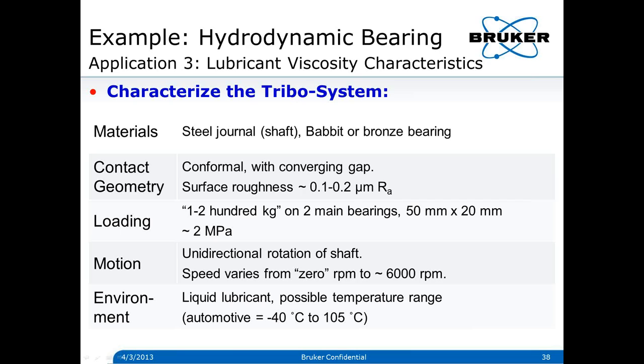Loading on a main crankshaft is roughly 1 to 200 kilograms on two main bearings about 50 mm in diameter and 20 mm wide — about 2 megapascals contact stress calculated as load divided by area. Motion is unidirectional rotation of the shaft, varying from zero to roughly 6,000 RPM. The environment will be a liquid lubricant with temperature ranging from about minus 40°C (cold mornings in Sweden or Alaska) to 105°C as limited by the water jacket with antifreeze.